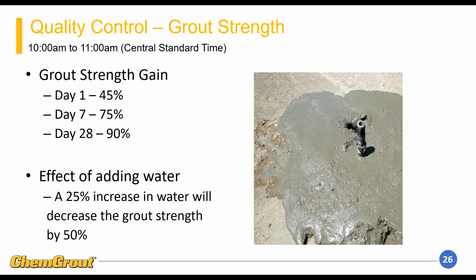The grout, cement and water gains strength during its hydration process, and it takes quite a while to fully hydrate the cement. So at day 1, you'll have about 45% of the total strength that you're going to gain. At day 7, you'll have about 75%, and at day 28, the day that most of the cubes are actually done for the final test, you'll have about 90% of the overall compressive strength of the grout.